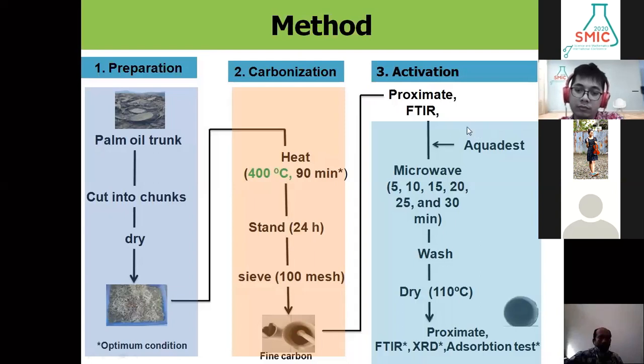After adding aqueous solution in some amount, the sample fine carbon is put in the microwave, and the microwave is run for 5, 10, 15, 20, 25, and 30 minutes, and then we will see the trends and we will get the optimum value. And then we will wash, dry, and then we perform again proximate analysis, also the characterization.